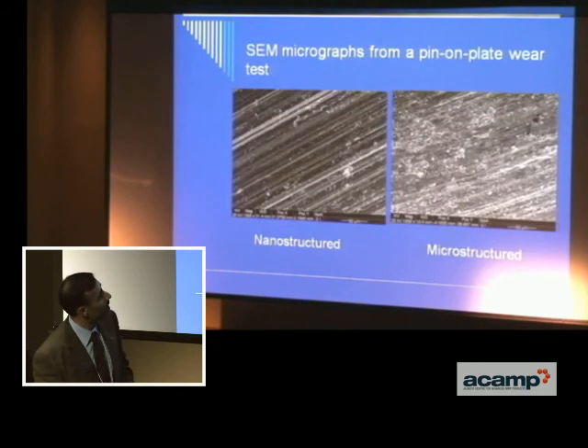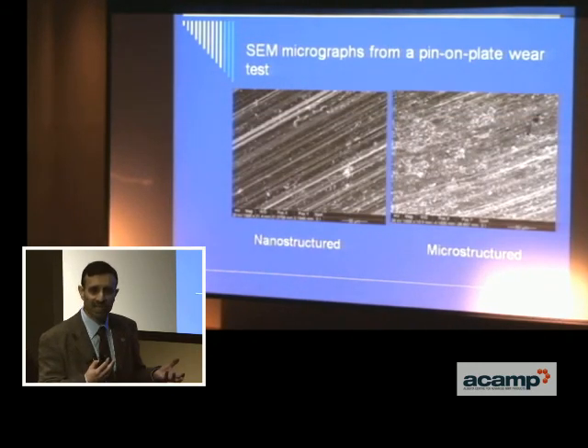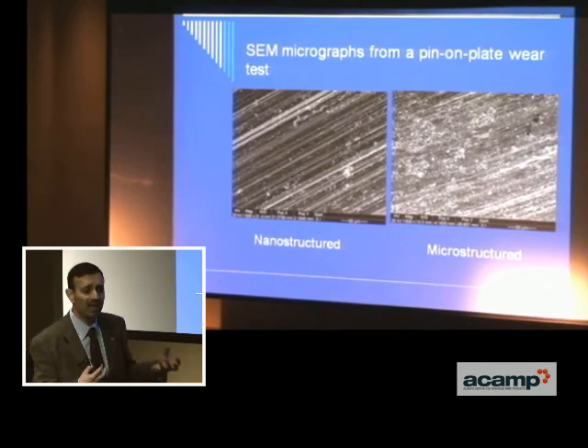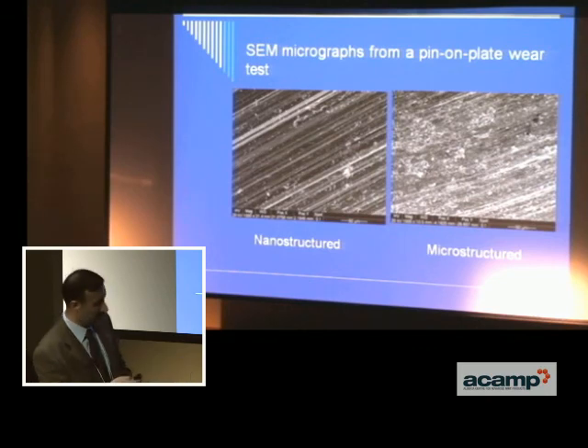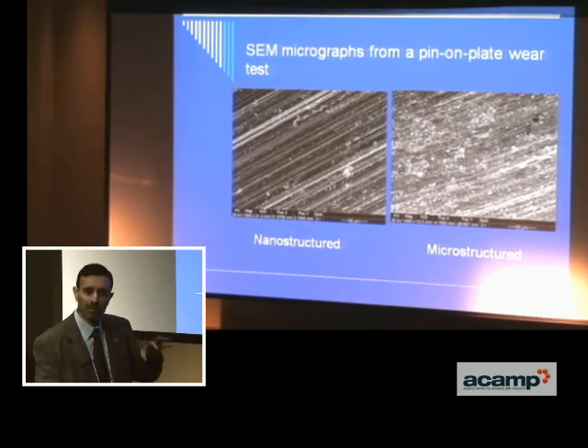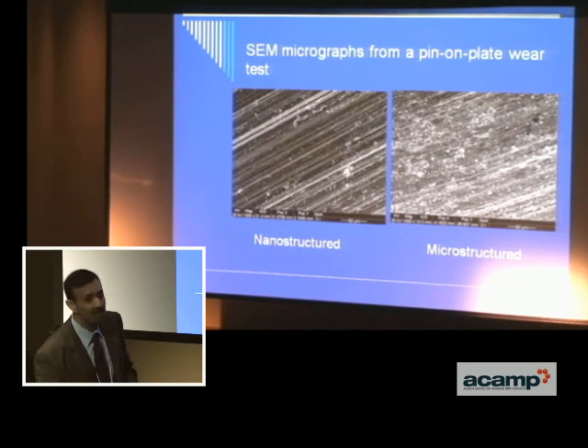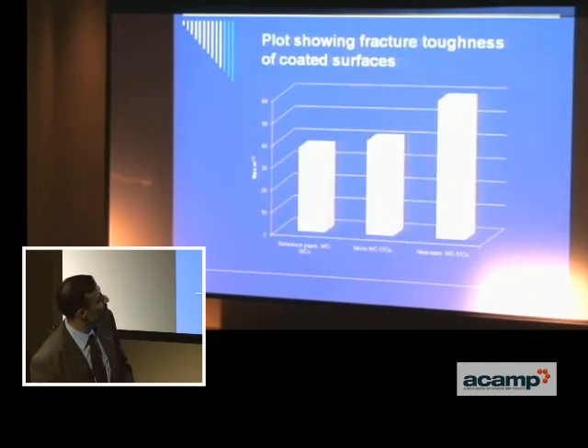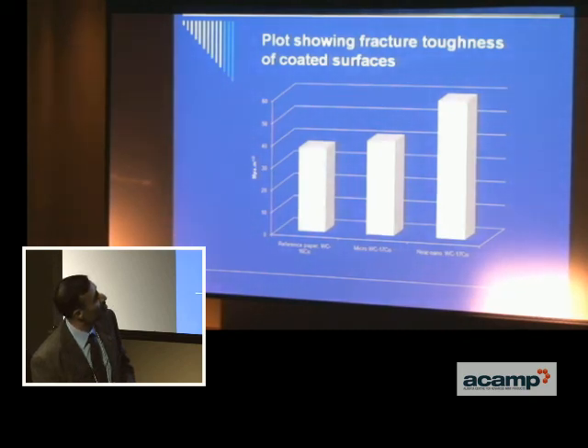So basically, there's a change in the wear process itself. Because we're maintaining the fracture toughness of the coating, we can expect a change in the wear mechanism. Here in the nanostructured material, there are these micro groovings, and that shows the material is still ductile and plastic. This is brittle fracture, and this is seen in the microstructured coating. This is a direct comparison of the changes in fracture toughness. Here we have our microstructured coating, and this is a nanostructured coating.